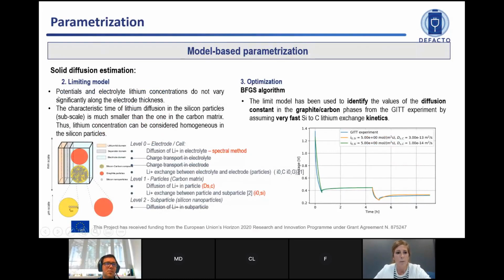First, an assumption is that the potential, both ionic and electronic, and even the electrolyte diffusing concentration, do not vary significantly along the electrode thickness and during the relaxation. Then, considering the characteristic time that we obtained based on literature data, which I didn't mention, it is much smaller than the others, so there won't be any concentration gradients, and we can assume a plateau.